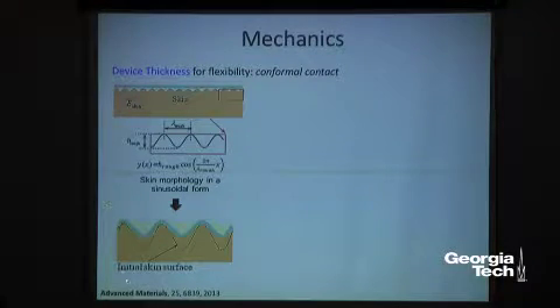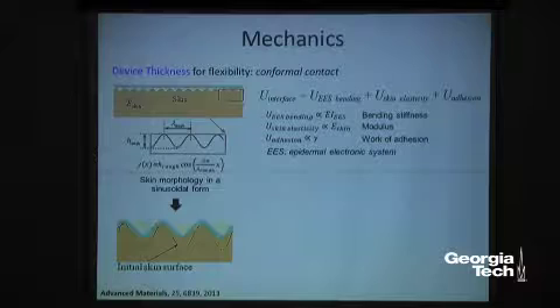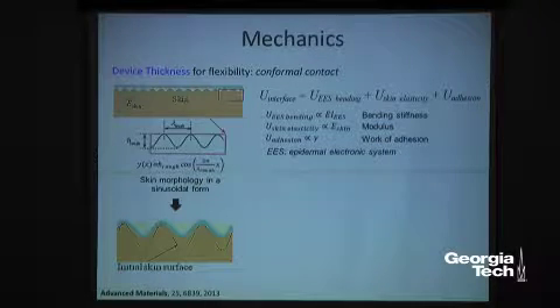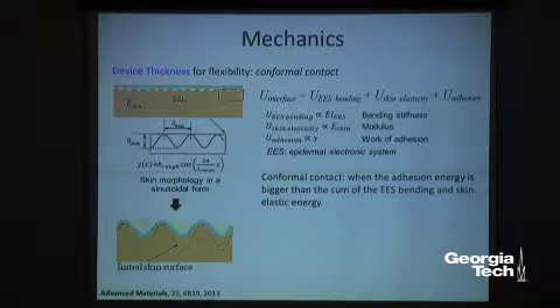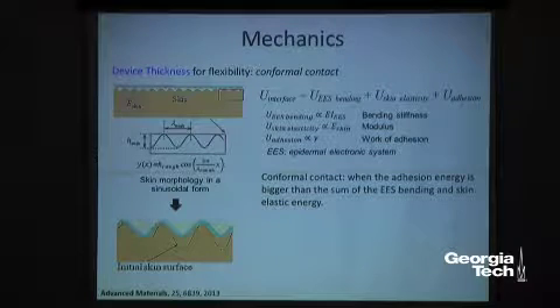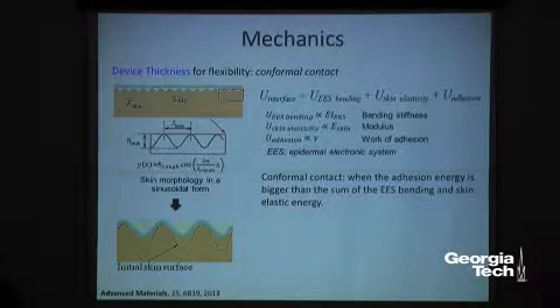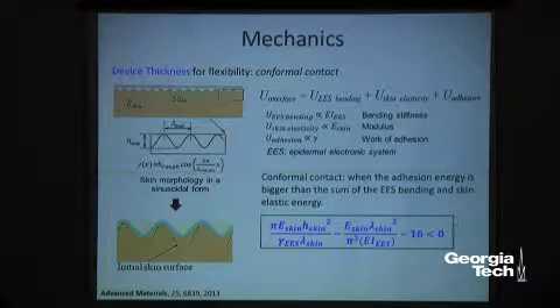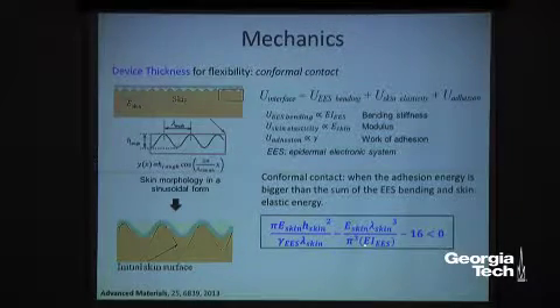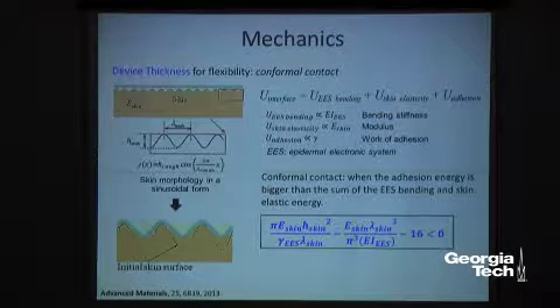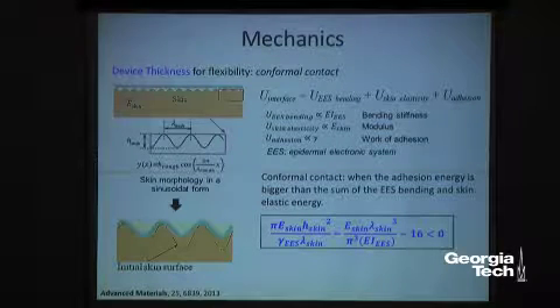And we consider this case where your electrode is having this nice conformal contact to the skin. At that interface, we can calculate this interfacial energy related to the bending energy of your electrode and skin elastic energy and adhesion energy. Right? So here in this equation, bending and elastic energy are negative and adhesion energy is positive. So this conformal contact can be determined when the adhesion energy is bigger than the sum of those bending and skin elastic energy. So by solving this equation, we got this governing equation having this skin modulus, amplitude, wavelengths, and so on, along with this EI term again, as I showed you earlier, bending stiffness, right? So this term is related to the thickness of your material.